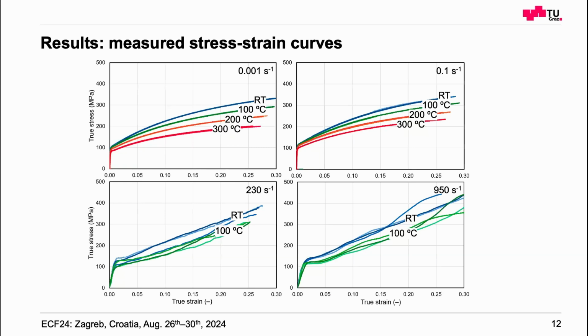Okay, I come now to the results. Here you see our measured stress-strain curves. We performed all the tests with 3 repetitions. For the lower strain rates, we have 4 temperatures determined. And for the higher strain rates, we also have 3 repetitions and these 2 temperatures.